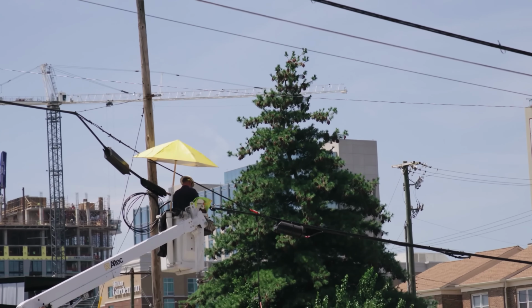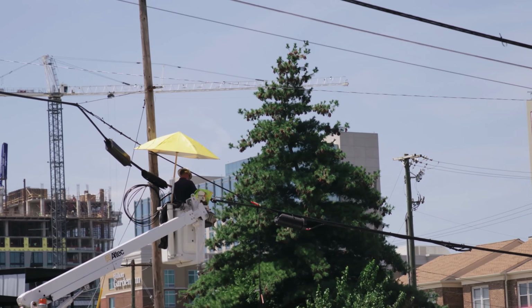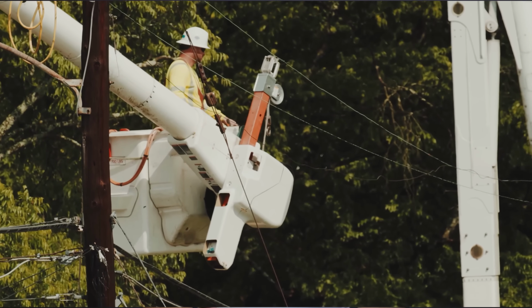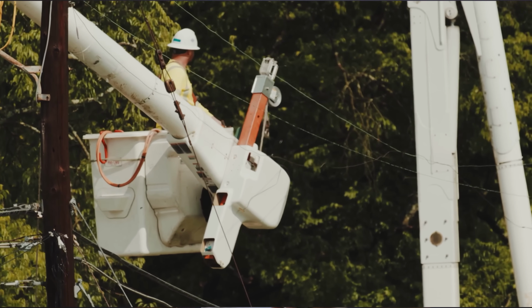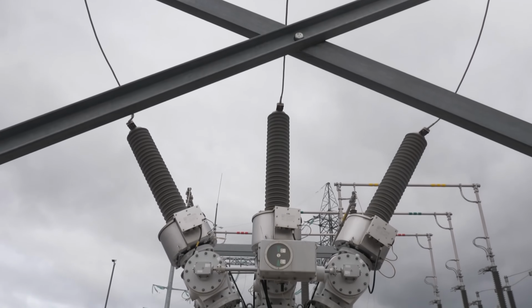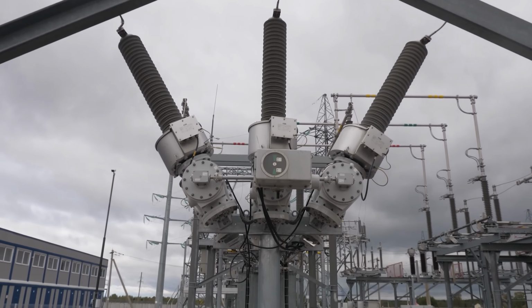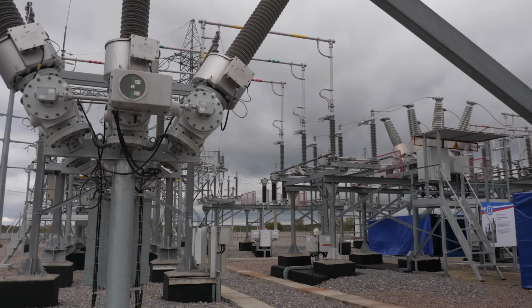Aluminum, and this is important here, faces its greatest challenges. Its ductility and malleability are lower than those of copper, making it more likely to break or get damaged if bent or handled with excessive force. But the biggest Achilles heel of aluminum is its tendency to oxidize. It reacts quickly with the oxygen in the air, forming a layer of aluminum oxide. The problem is that this oxide is not a good electrical conductor, and in fact it's an insulator. At connection points, this layer can drastically increase the contact resistance, causing excessive heating and, in extreme cases, fire hazards.